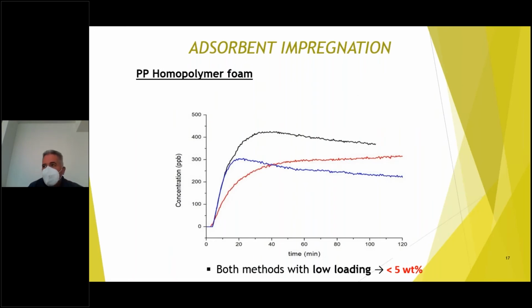This is really the conclusion that we arrive at with adsorbent impregnation. With these methods we reach low loadings, lower than 5% of MOF inside the foams. Turning back to the methodology to measure acetic acid absorption that was presented by my colleagues from Lisbon University, we can see that after 2 hours of exposure to a concentration of acetic acid, this kind of foam has practically not absorbed any acetic acid. The acetic acid, after 2 hours, practically maintains its concentration. This means that we have a very low concentration of MOF, and it's not working as we expected.